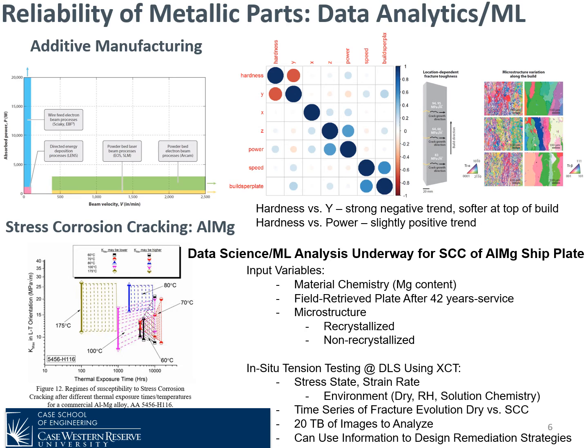So I've covered the bottom region here, stress corrosion cracking. We know what the material is, we've characterized it, we've tested it already under dry and under stress corrosion conditions, and we have a series of images now that show the evolution of fracture dry versus stress corrosion. And there's about 20 terabytes of images that Kaylee will be helping us along with the other members of the team. The unique aspect of this is that we also may be able to use this information to design remediation strategies. I close with, we also have additive manufacturing work going on over quite a wide regime, and that may be of interest to some of the collaborators.